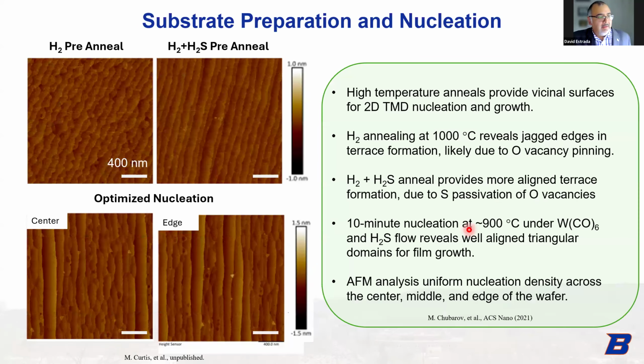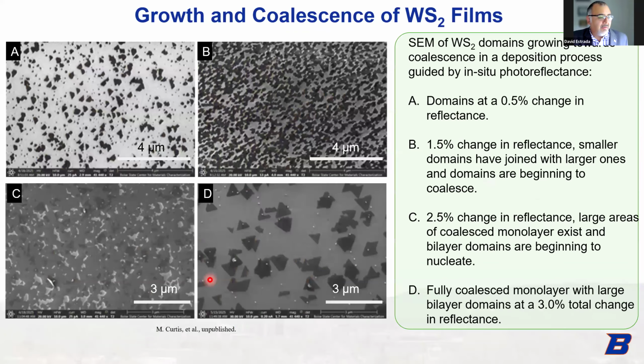Here's an example of our substrate preparation and nucleation. Here's the hydrogen pre-anneal and the hydrogen plus hydrogen sulfide pre-anneal. We see a nice reconstruction of the sapphire surface, getting the nice aligned terraces that we saw in Professor Redwing's work. Then we can switch to nucleation, and you can see the small triangles nucleate at the edge. This is WS2. We're nucleating at 900 degrees Celsius under tungsten carbonyl and hydrogen sulfide flow, and we do see some good alignment, suggesting we might get good epitaxy in the growth.